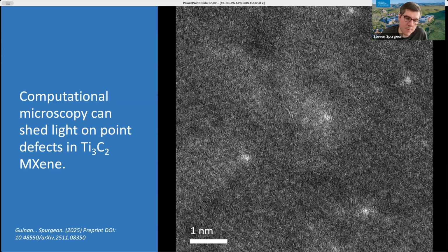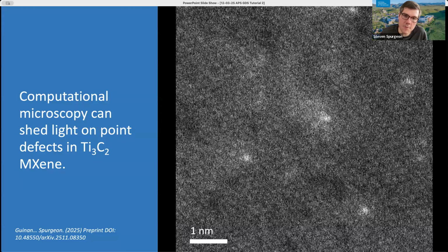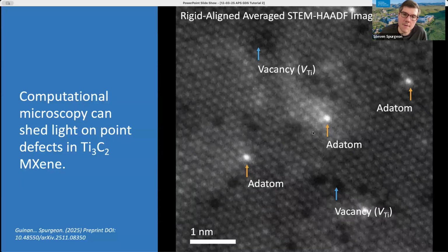So what we typically do when we analyze these materials is we take this raw data and perform a registration. We stack the data after doing a rigid and/or non-rigid registration of the images. We can improve signal to noise, and then we can start to make some sense of what's happening. Now, we've obviously lost time information when we do this. There are some things happening between frames that we're averaging out here, but this is the only way that a human can interrogate this data. What you find in these materials is the lattice of the MXene. The brighter spots in the imaging are actually adatoms on the surface, and the vacancies here are missing titanium atoms within the MXene lattice. So through this imaging, we can directly interrogate these materials.